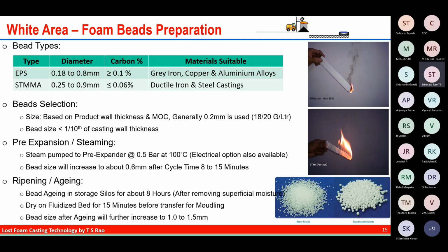Once the steaming is done, the third process is called ripening or aging. Bead aging: again, we have to transfer the expanded beads into aging bins. They look like silos, storage silos with a lot of ventilation in all directions, and approximately 8 hours we are supposed to hang the beads in hanging silos after removing the superficial moisture.